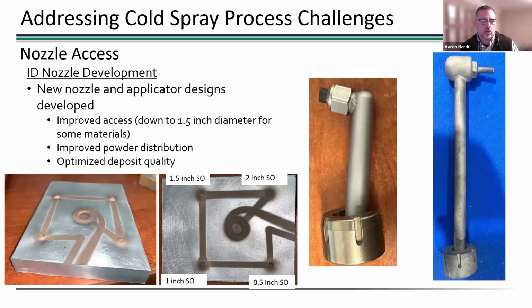Nozzle access, we've done a lot of work recently on new ID nozzle geometries to be able to get into diameters as small as 1.5 inches, and also be able to get very uniform depositions with those materials. Traditionally, when you start turning a corner with the cold spray material, you can end up with all of your powder on one side of your nozzle, for instance. You still can get a good deposit, but in certain cases that can cause you problems and it causes you irregular wear of your nozzle. These two new designs are based on a couple different concepts of eliminating that, and you can actually see from these patterns that we're getting a nice ring pattern of your powder. It's uniformly distributed within your nozzle now, so you get more uniform wear and erosion as well as a better build.